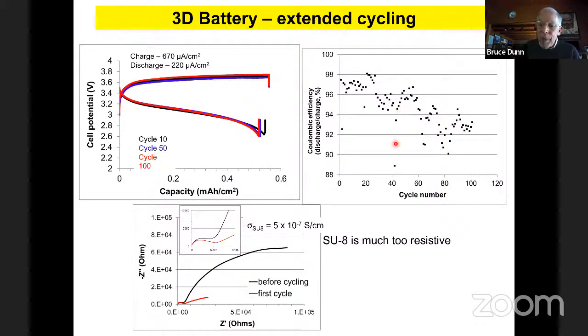What's the source of the problem? The problem is the electrolyte. It's much too resistant. The conductivity of SU8 is on the order of LiPON, maybe just a little bit higher. But when you put it together in a device that's 10 microns thick, you have much too high a resistance. It's going to be on the order of thousands of ohms. You can't afford to have cell resistance at that high a level.